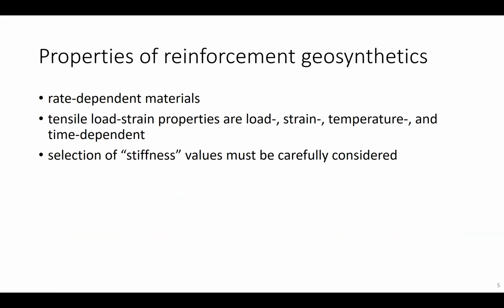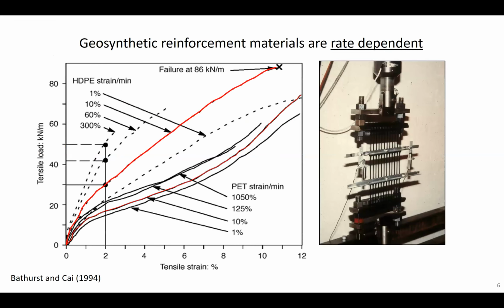The challenge is that reinforcement geosynthetics are rate-dependent materials. This means that their load strain properties are load, strain, temperature, and time dependent. And this makes the selection of stiffness values a challenge and something to be carefully considered. And I can demonstrate this by looking at the results from some constant rate in-air tensile tests.